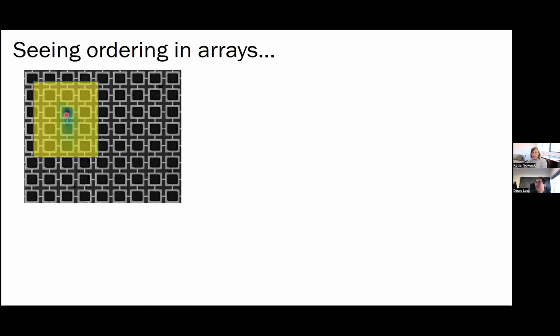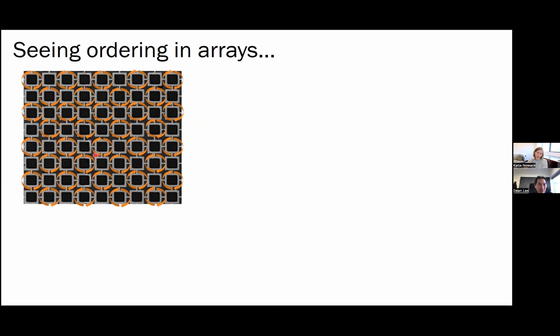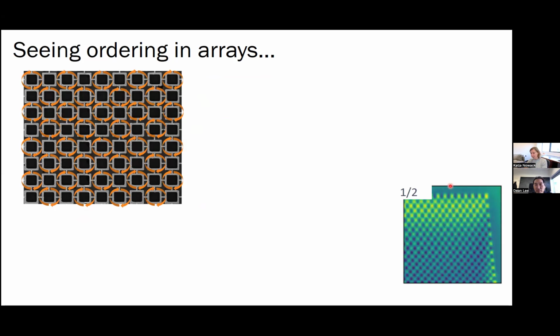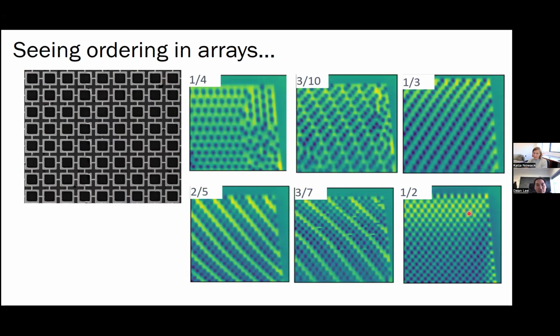We can control the number of vortices in the structure by applying a little bit of field to the structure. If we apply enough field that about half of these plaquettes want to trap a vortex, then we get a pretty image like this, where you get this checkerboard pattern. That's what we call filling 1/2. That means that we apply enough field that 1 out of 2 plaquettes traps a vortex. We can, of course, also go to other fractions and discover these very beautiful vortex lattices and regular arrangements. These regular lattices form because vortices interact with each other. They're a result of vortex-vortex interactions that drive them to form these very periodic structures. And this is quite beautiful.